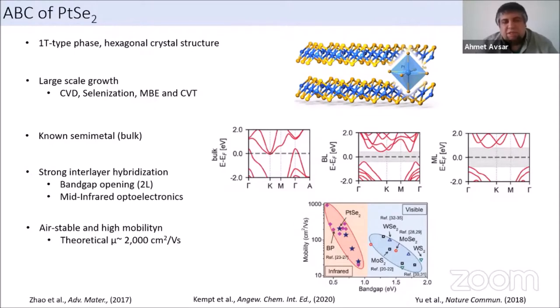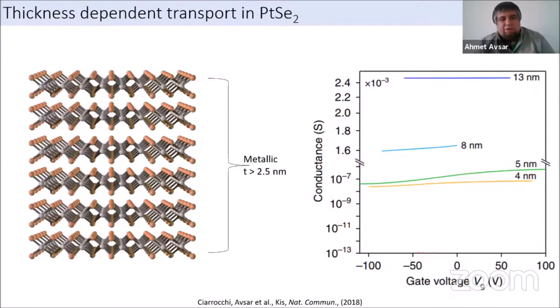But the advantage of PtSe2 compared to black phosphorus is that PtSe2 is air stable. I will show you later, but for instance, many of these 2D materials like black phosphorus or chromium iodide, if you isolate them and put them on a table for half an hour, you just see that the materials are completely disappearing. In the case of PtSe2, it has long-term stability, even in ambient conditions at the monolayer limit.